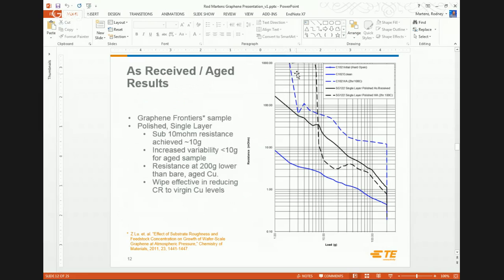So if we walk through the exercise once again, the blue curves are the copper. So the copper, before we electrocleaned it, this would be copper that has just been in the lab for a couple of years and has a normal oxide on it, was open circuit. We electroclean it, we make it clean, we bring it down to the lower blue curve here. And then we heat age it, and it comes back up to the dashed blue line. So we know that, okay, that's where oxidized copper is going to be. Now, if we look at our graphene-coated samples, the solid line is the graphene as received. And once again, it's certainly lower than the open circuit copper.